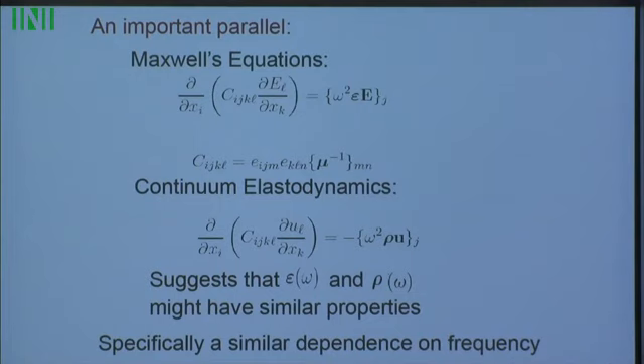If you just make a comparison between Maxwell's equation, here E is the electric field, and continuum elastodynamics, here U is the displacement field, rho is the density, C is the elasticity tensor. Here you've got a tensor C, which, as opposed to the elasticity tensor, is anti-symmetric in the first and second pair of indices here. EIJM is the Levi-Civita tensor taking values plus or minus 1, depending if this is an odd or even permutation. So when you write them this way, they look very similar, and that actually suggests that the dielectric constant as a function of frequency and the density as a function of frequency may have similar properties.